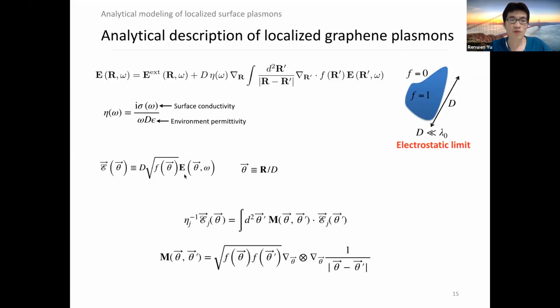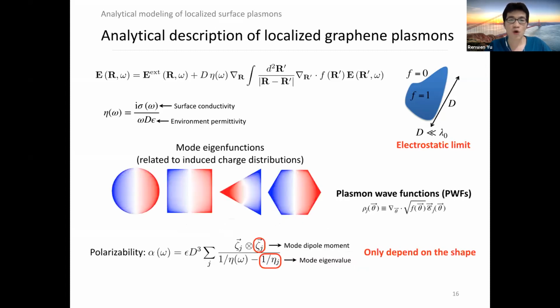And after defining the normalized field and the normalized spatial coordinates, we can get this eigenfunction equation, where E_j is the eigenfunction, capital M is the non-local operator, and the inverse of eta_j is the eigenvalue. After solving this eigenfunction, we can obtain the so-called plasmon wave functions, which are related to the induced charge distribution. The blue and red colors indicate charges with different signs, positive or negative. And the optical polarizability can be decomposed as a summation of all these optical modes supported by these graphene nanostructures of different shapes.